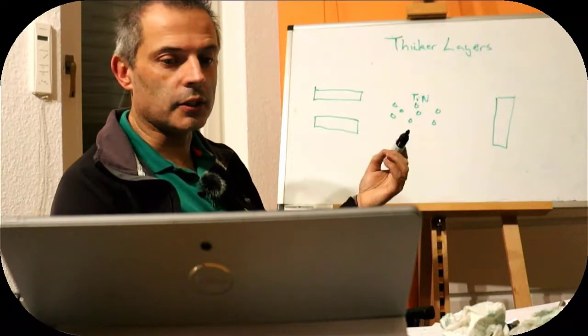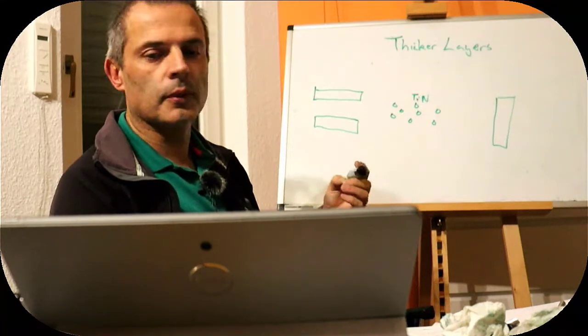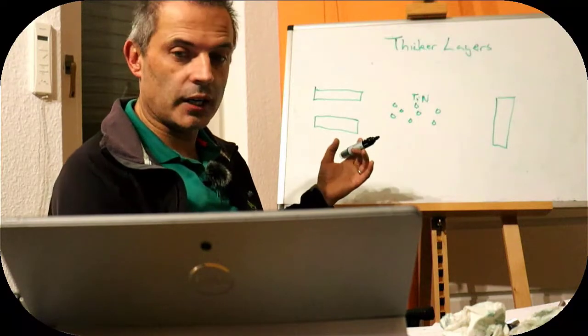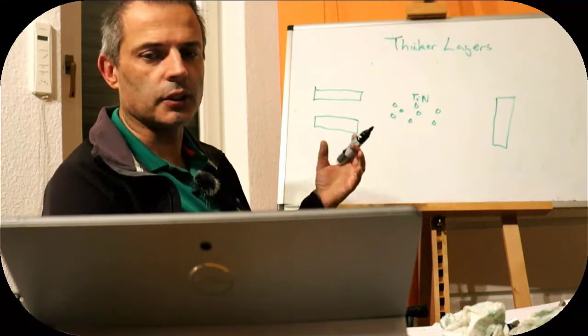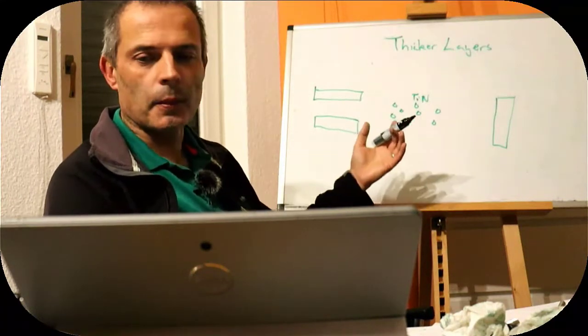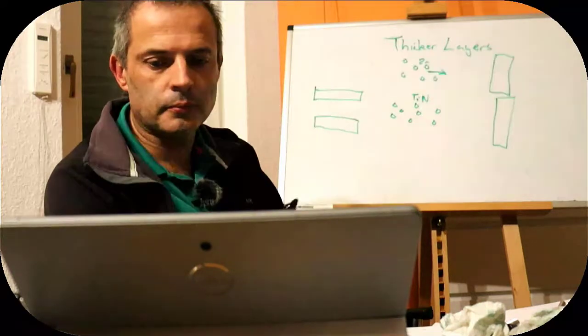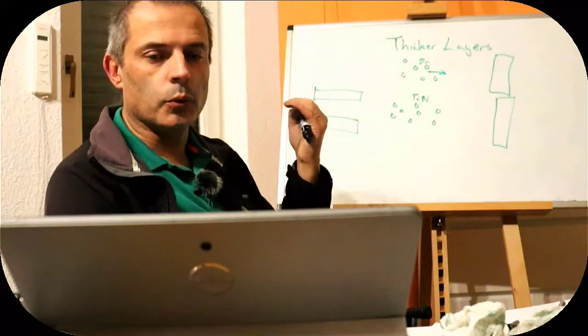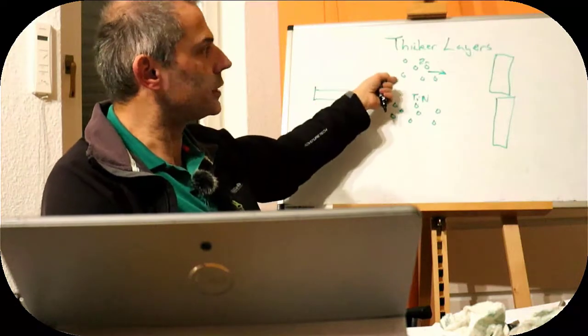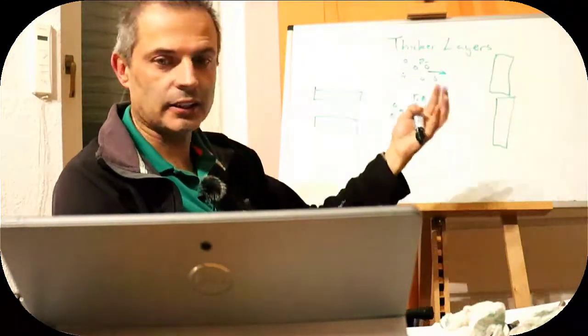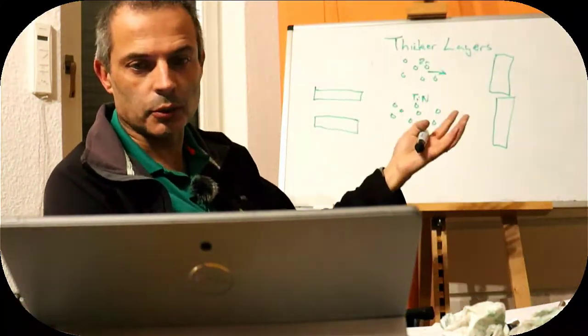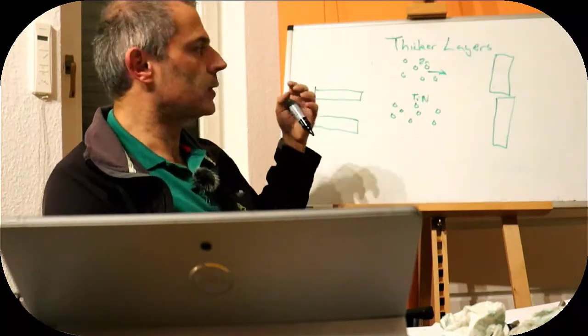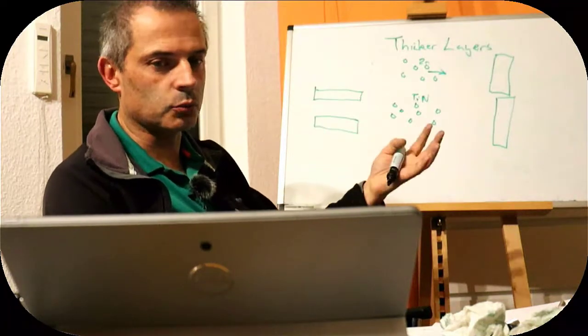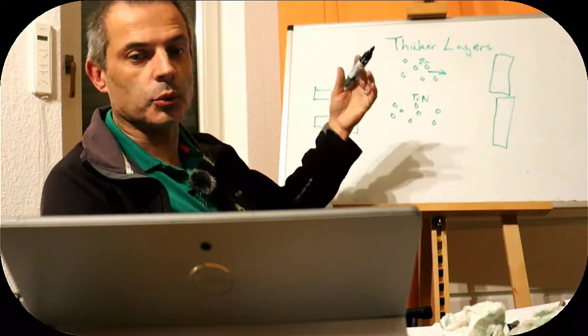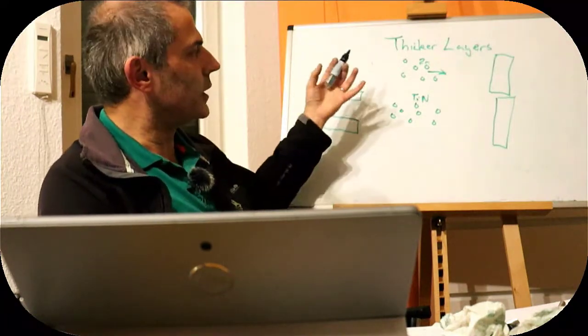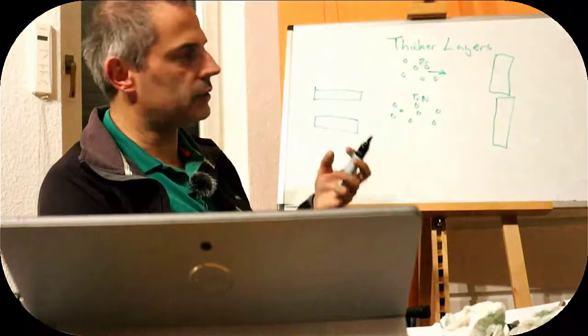What we need them to do is to get there with enough energy that they melt on arrival. There are a variety of ways of doing that, so we either heat them up beforehand, or we can heat them up purely with the kinetic energy. It's not going to work with titanium nitride because they need to get up to a very high temperature indeed, but it would work with some materials. So if we imagine we've got some zinc metallic particles, we can conceive that it is possible to get them to go fast enough that when they whack into the surface they will melt, or maybe not melt, they will at least cold weld with each other. In reality, it's possible to get them hot enough from hitting the surface and working that they will actually melt, and that is if we get them going very fast indeed. Obviously, they're typically supersonic when they get there, and they will be blown by a very fast type of gun.